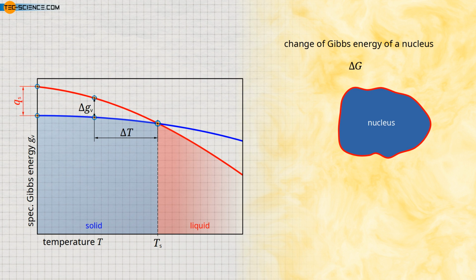The change in the Gibbs energy of a just solidified nucleus when the solidification temperature is undershot can thus be mathematically attributed to two essential terms, which are explained in more detail in the following. The term marked in blue results from the already explained lower Gibbs energy of the solid state compared to the liquid state. As long as the temperature is below the solidification point, this term is always negative. This is because the solid state below the solidification point has a lower Gibbs energy than the liquid state. This means that below the solidification temperature, the energy content of the solidified nucleus volume is lower than in the liquid state by the amount delta GV.